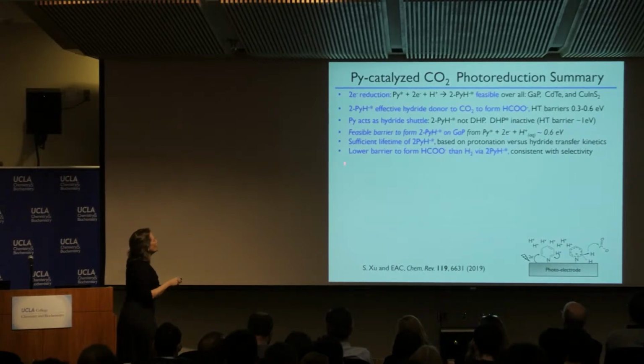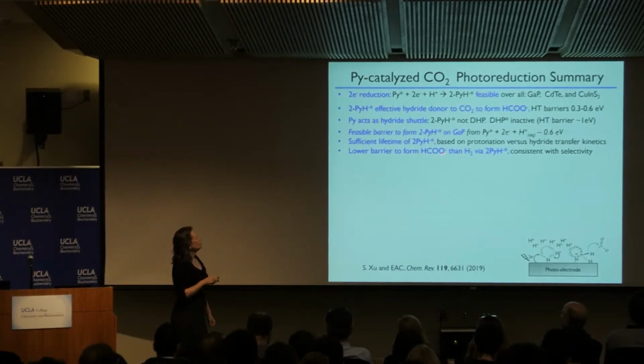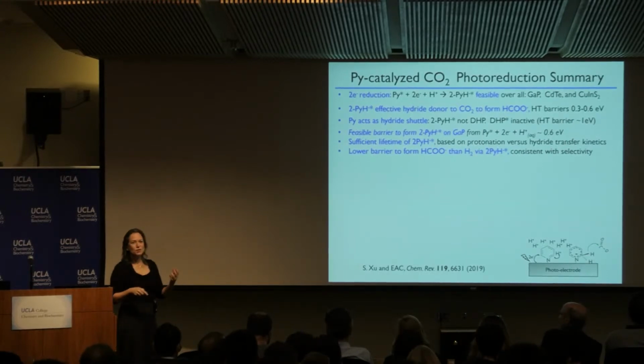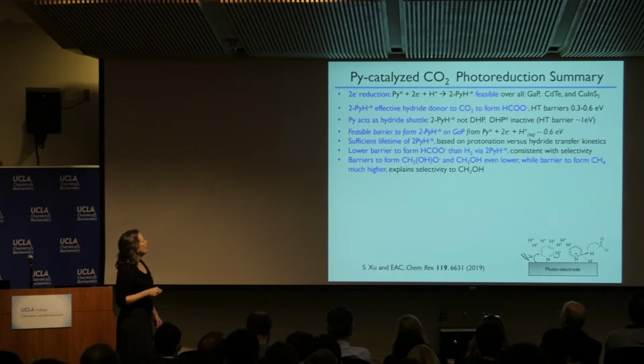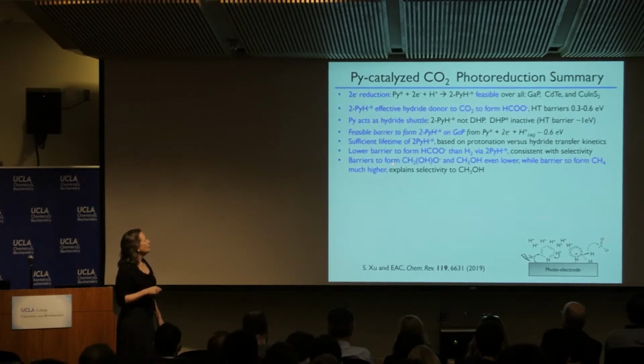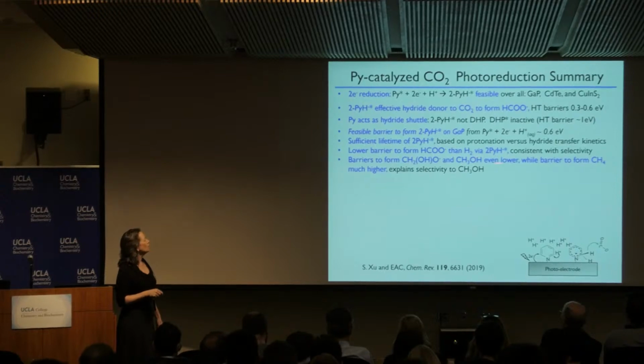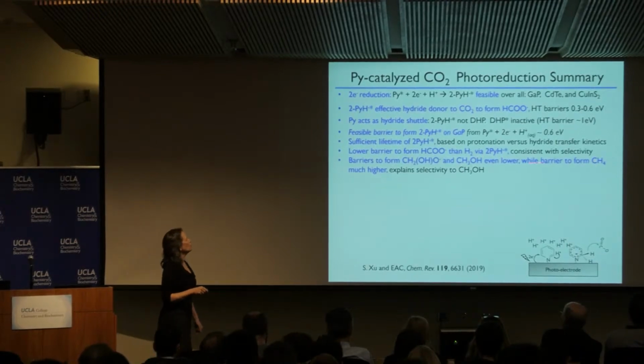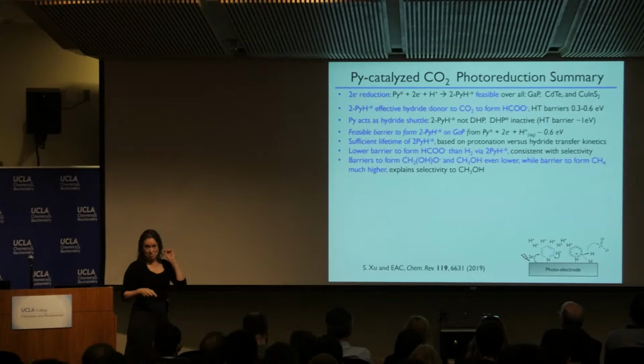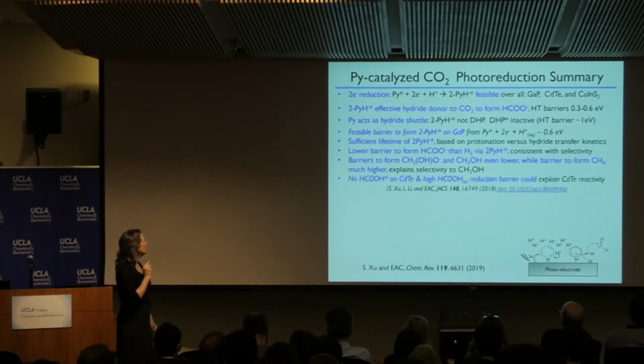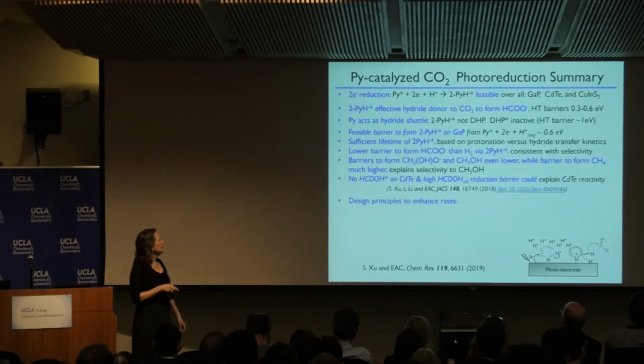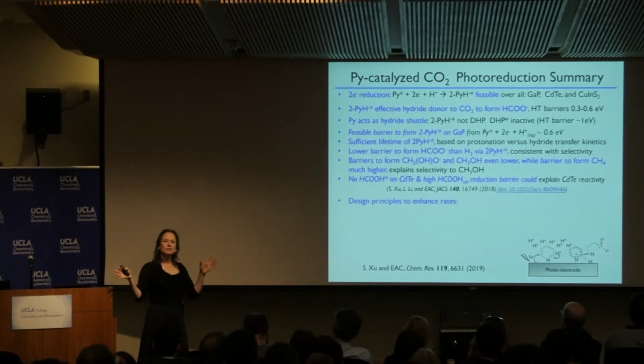We also showed that the barrier to form formate is much lower than to form hydrogen. That's consistent with the known selectivity. And I showed you that the barriers to form these species on the way to methanol are even lower, whereas the barrier to form methane is much higher, and that explains why you get methanol selectively and not methane. Didn't talk about this, but we can understand potentially why on CdTe you make formic acid. Anyway, that's a bunch of explanations.